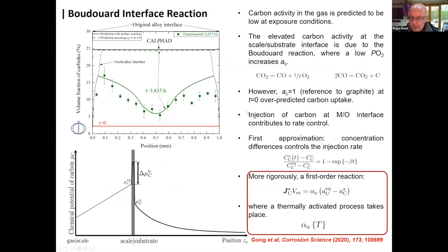When we first started to model this effect, we did this in a rather empirical way, just by assuming that the concentration evolved using an exponential term, consistent with this expression here. And then when we really started to think about this, we realized that this first order reaction is what we needed to do, where now this Robin boundary condition is a function of temperature. So I'm going to give you some data in just a few moments about that parameter.